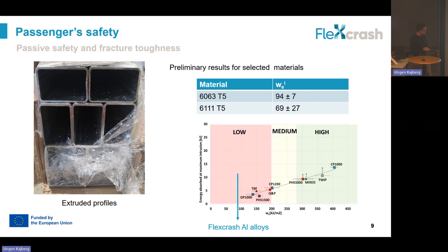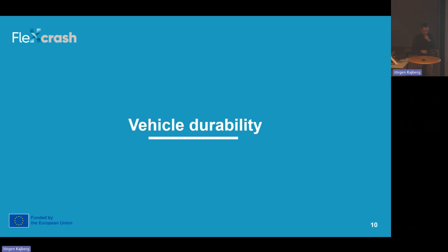And here I also put this graph where we are comparing this energy absorbed at maximum intrusion. So this is a case of a component, or these extruded profiles, represented against the essential work of fracture. So we have a linear trend, just to show that it's a good property to assess the energy required to crash a component. This is for advanced high strength steels, and of course in this case the aluminum alloys are a little bit lower, but we can see a difference between these two different materials. So then we have, on one side, this essential work of fracture test to assess the crash behavior of the material. So we have a strategy to select the best material for crash scenarios.